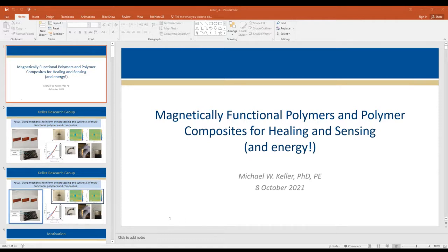And the normal way that you do encapsulation is you use an emulsion. So I have an oil phase core, I emulsify it, I put some chemistry into the water, and eventually it hits a critical molecular weight and crashes out to the interface and builds the polymer shell around the liquid drop. We can't do that with water, because I'd have to do a water and oil emulsion. I don't know if you've ever interacted with that, but they are difficult to stabilize, for a bunch of reasons. So we needed an alternative method.